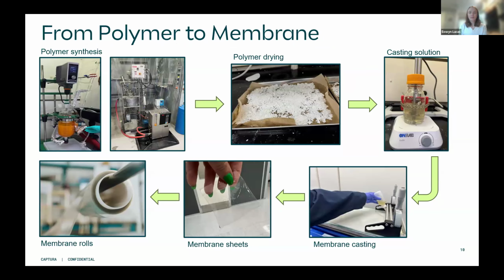So this is a bit of a flow diagram here of the polymer to membrane process. As I mentioned, we started at a much smaller scale. It's not actually even imaged here, just very small few milliliter bottles. Then we moved up to a five-ish liter reactor. Now we're at 20 to 50 liter reactors, as you see here. Once we make the polymer for the membrane, we dry the polymer and you end up with this kind of powder that you see here.